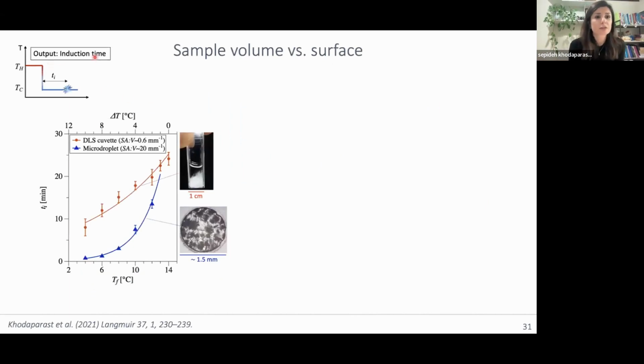So let's just start with an isothermal test, which is the easiest for comparison of data. So we cool down the solution below the crystallization temperature, and we wait and measure the time that it takes for the first crystals to form. I'm showing you the result from two different techniques. The first technique is dynamic light scattering, which uses a laser. The second one is optical microscopy.